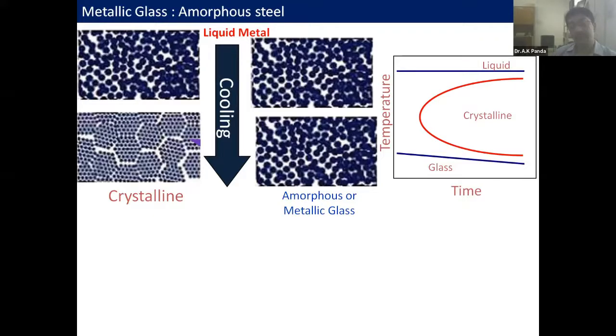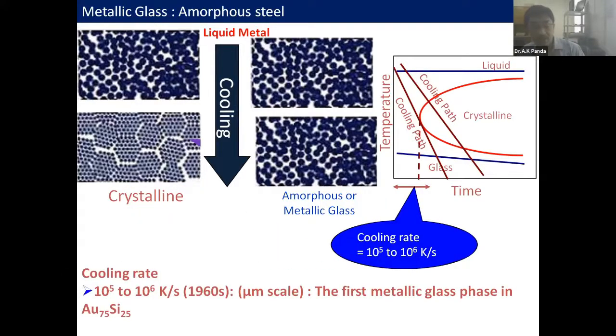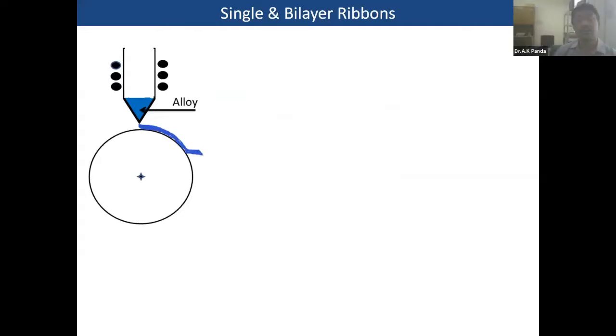Now this is the typical temperature-time plot, and this is the curve for the crystalline phase. What happens actually, if you try to pull down the metal, you intersect the crystalline path, and you always land up in crystalline materials. Whereas if you try to avoid that, if you want to make it very rapid, you try to avoid the nose of the crystalline phase, then you have to cool it very fast, and it is like 10 to the power 5 to 10 to the power 6 Kelvin per second. And possibly this could lead to some amorphous materials. And the first one was like a gold silicon. I'm not going into details of amorphous. I'm trying to concentrate on materials like bilayered ribbons, which you can use for magnetocaloric property evaluations.